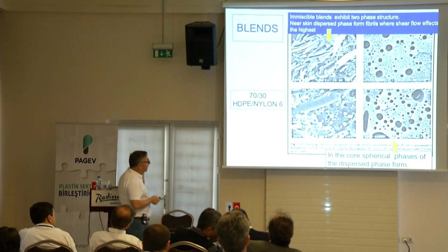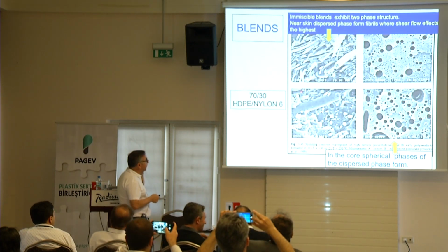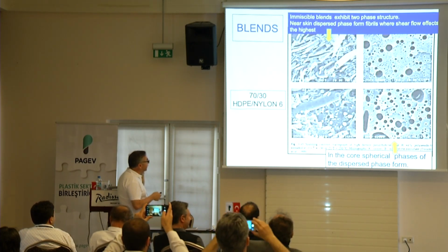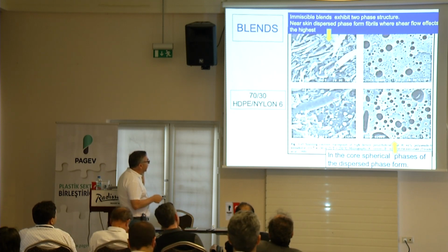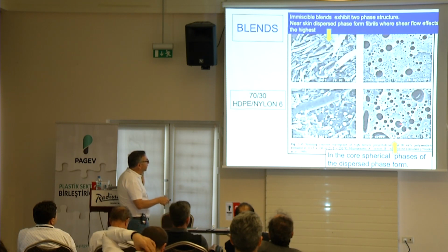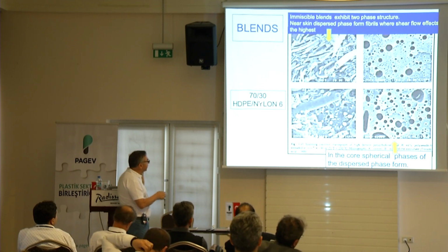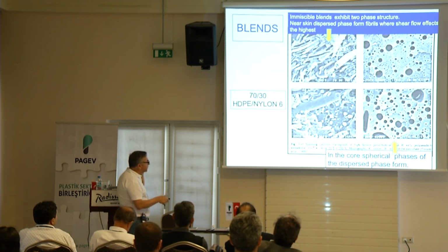Blends, in the case of blends, especially when they are not miscible, like nylon and polyethylene, in the skin you will have all these fibers, and the core will be dominated by the spherical dispersed phase. This is a typical behavior in the case of immiscible blends. This is 70% polyethylene and 30% nylon. And in this case, nylon is the dispersed phase, and nylon is orienting near the skin. That's pretty much it.